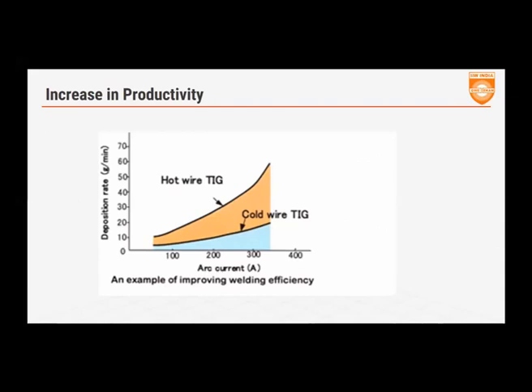By how much? Typically, when we are talking about manual welding, we're looking at welding at about 200 amperes at best. So you're looking at cold wire fed at about 10 to 12 grams per minute. And when you do the same with hot wire, you are looking at about 20 to 25 grams per minute manually fed, which means you will have quite a significant difference in your productivity.